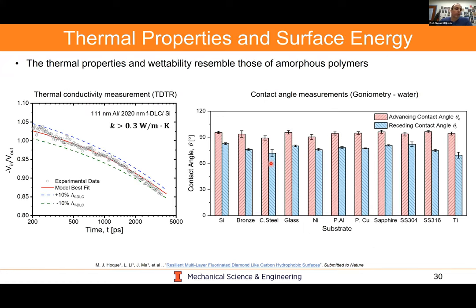If we were to look at the thermal conductivity, we see that it does have a polymer-like thermal conductivity of 0.3 watts per meter Kelvin. And what we're plotting here is the contact angle as a function of substrate. You could see that we could actually make this very versatile for a range of different substrates, it works quite well. There are a few substrates where it's hard to do this deposition, but for the majority of engineering-based substrates, we actually get fantastic performance.